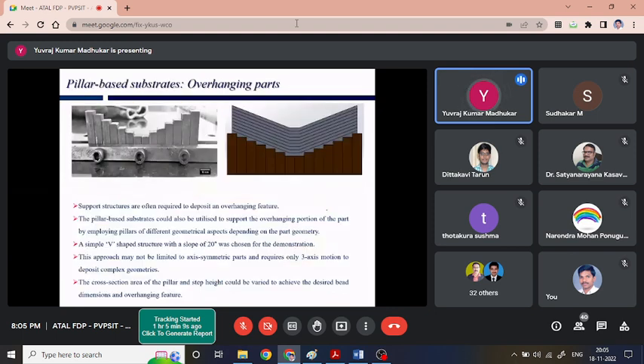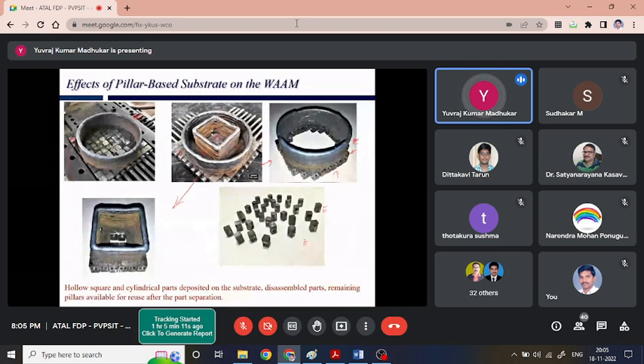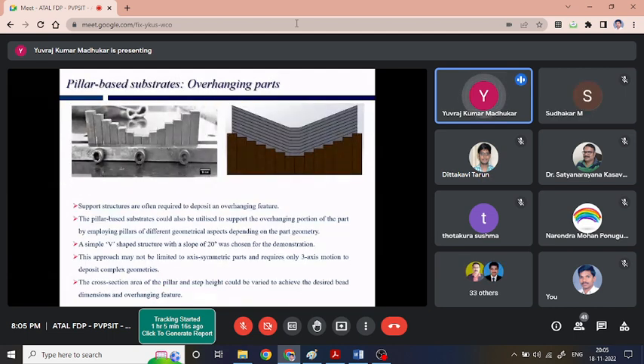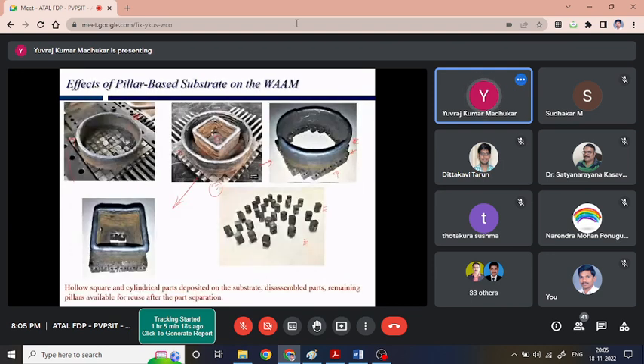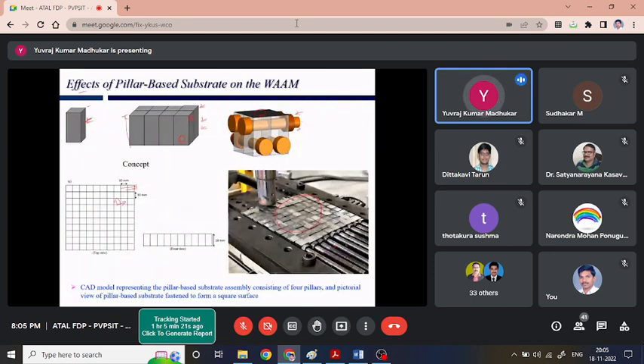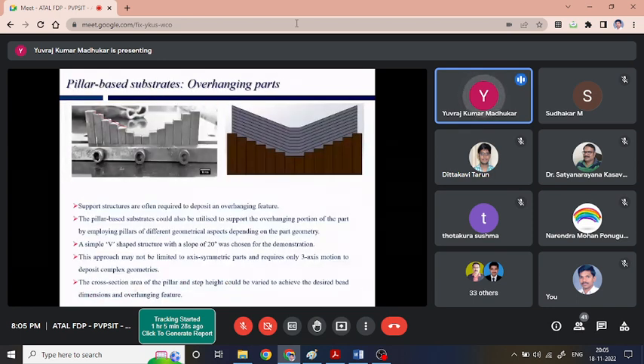Now here, what if we could achieve this kind of a deposition? If the concept works over here, we can think of changing this pillar height. Instead of taking these pillars of a constant height, we can change the height of a pillar in a certain pattern. For example, here we change the pillar height in a certain V pattern. Just the step size we have to optimize, so that we ensure the deposition is taking place over here, and we should be able to deposit this kind of an overhang feature for the WAAM application as well.